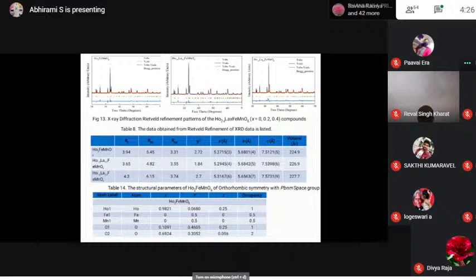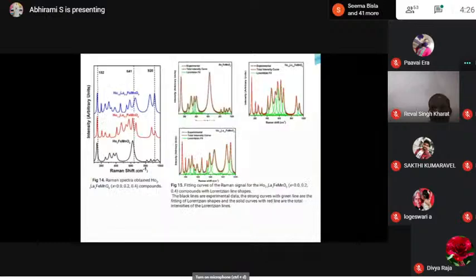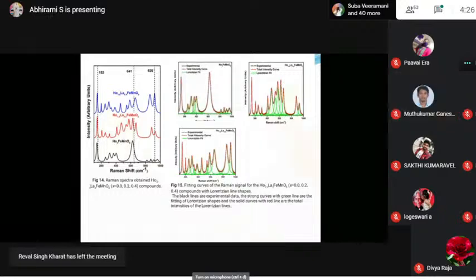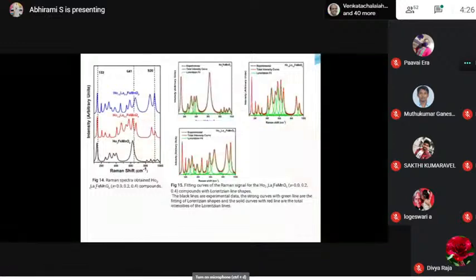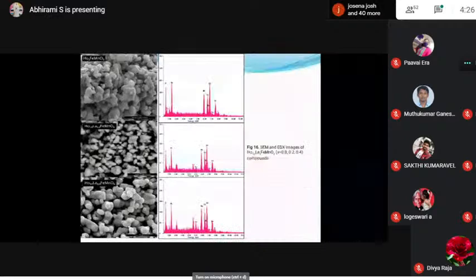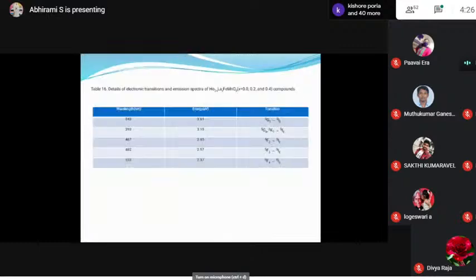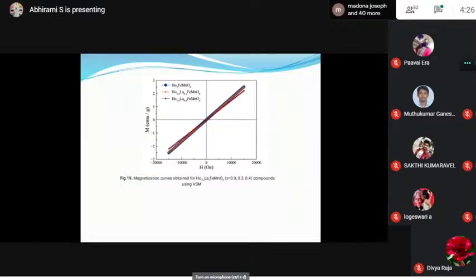The prepared compounds are all in the Pbnm space group. These are all my Raman studies, micro Raman studies, and the fitting curves of the Raman signals from the Ho2FeMnO6, and two more combinations are shown in the figure. These are my assigned Raman modes of the prepared compounds. These are the SEM and EDAX images of my compounds. This is the magnetization curve obtained for the La doped compounds.